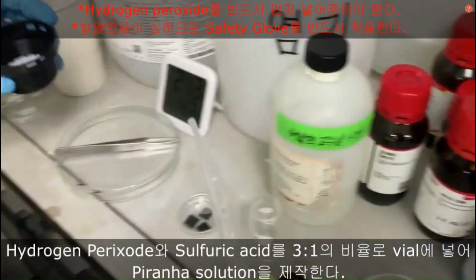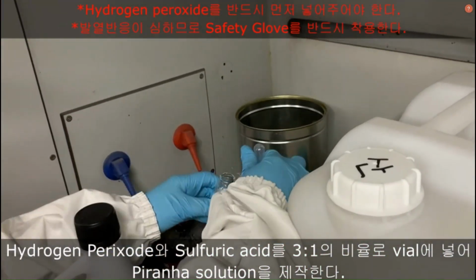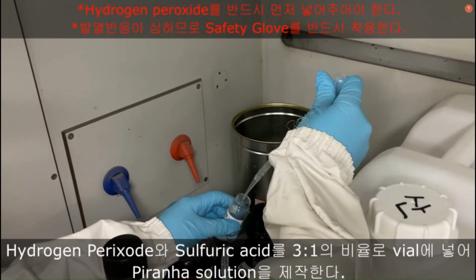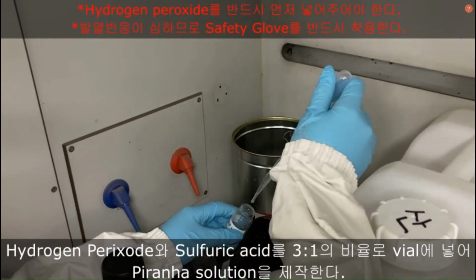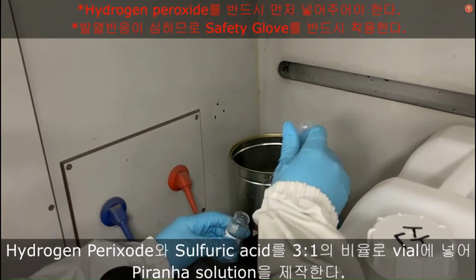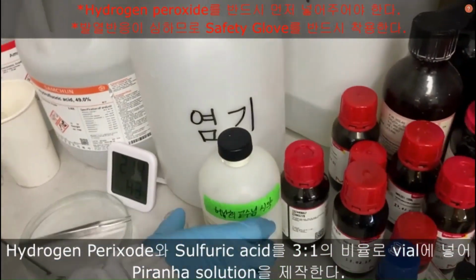Prepare the piranha solution by mixing hydrogen peroxide and sulfuric acid in a 3:1 ratio. You should be careful when handling piranha solution. You must put hydrogen peroxide before sulfuric acid, and you should wear safety gloves.